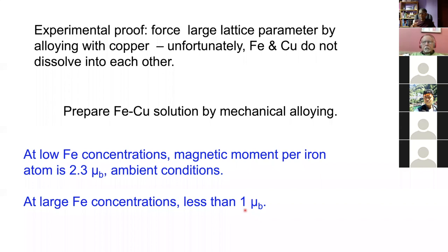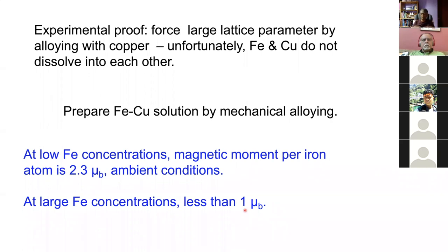In today's lecture, using only what we've learned in the first two lectures, we can apply thermodynamics to study real materials of practical importance — both in materials engineering and from a fundamental point of view. If you ever need to make a strange alloy that phase diagrams say should not be possible, this is a technique you can use. Laboratory-sized ball mills exist; you can make them yourself using ball bearings instead of cast iron balls. Industrial-scale ball mills also exist for larger quantities. The main challenge is the consolidation step, requiring extrusion or hot isostatic pressing so atoms don't move about too much during the process.